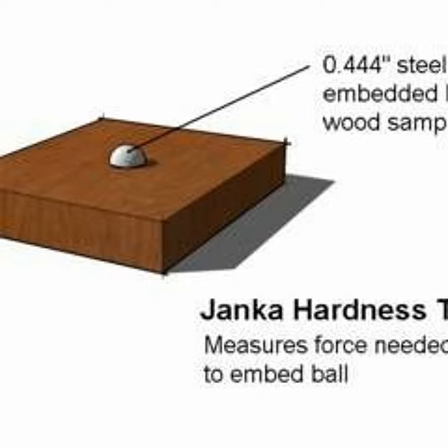So while they are in a direct relationship with one another, you will find that it can be particularly telling if you compare one species to another. If you've got two species of similar Janka hardness, but you're like, man, this one is a lot harder to work, more than likely you're going to find a difference in density. Moreover, if you're in a part of the world like Australia, where just about all the woods are super hard on the Janka scale, you can look for species with a lower density and find that they're a lot easier to work. Even though the fibers themselves are quite hard, because there's more dead air, because there's a less dense surface, you will find that it feels easier, and the resultant hardness is actually quite a bit lower.